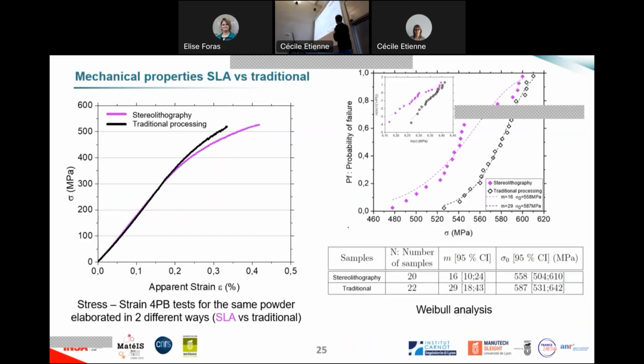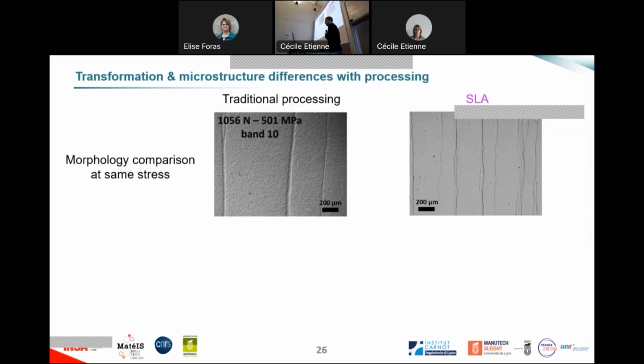But here what we saw is that we weren't able to achieve exactly the same distribution of strength because it was the first development of this material. So we want to improve the distribution to make the material more reliable. So what is the parameter to look at here? It's the M, the Weibull modulus, which shows us that with our traditional way of processing these materials, we had a better distribution, so a thinner distribution. You see that the lower strengths were higher than the lower strengths we have for the pink ones. So this is where we can improve on this stereolithography for these samples.